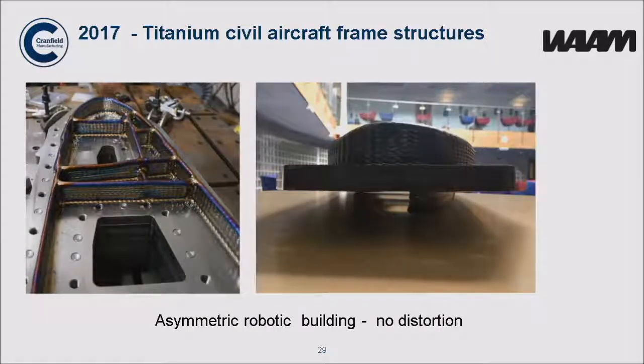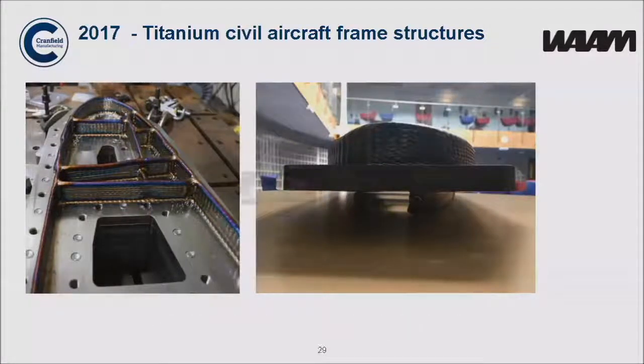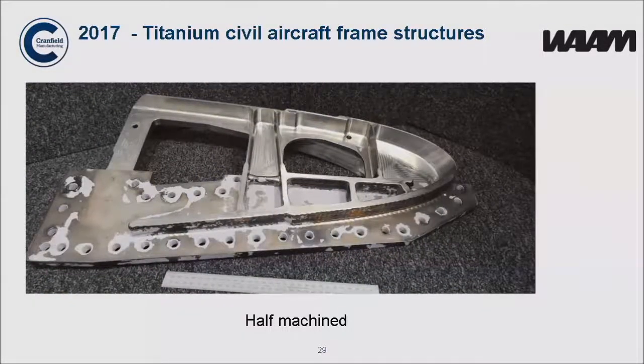A lot of the parts we make are symmetric because this deals with the distortion issue. But also, if we have asymmetric parts, then we can manage that as well. This is a D-nose section for an Airbus aircraft. And you can see it's very asymmetric, but we have no distortion in the part. And you can see here, this is the part after it's been half machined.